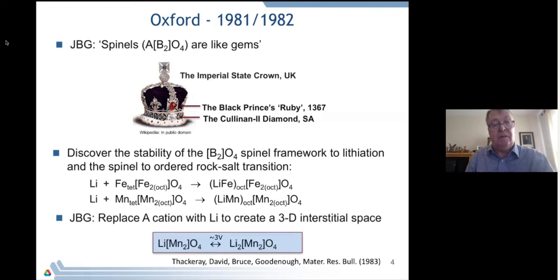I remember Bill David and I, who had just done the work on the Fe3O4 and noticed these structural features, we took the results to John, and it wasn't 5 seconds or 10 seconds before John said, well, if that's the case, what we have to do is to replace the tetrahedral site cation with lithium. And that was the start of the lithium manganese oxide project. Peter Bruce joined the team as the